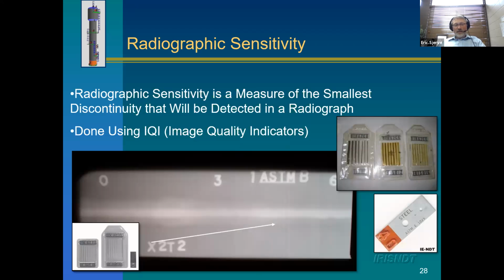The other thing we deal with is sensitivity. Just like with ultrasonic testing, where we had the second part of that calibration dealing with sensitivity with the ASME block, with radiography we need to know what the sensitivity of the technique is. Just like the other techniques, we don't want to be telling the customer there's all kinds of super small defects and they're rejectable, but we also don't want to be so insensitive we're missing big defects that will lead to failures. We do that with something called an IQI, which is an image quality indicator, and those are just wires of different diameters.